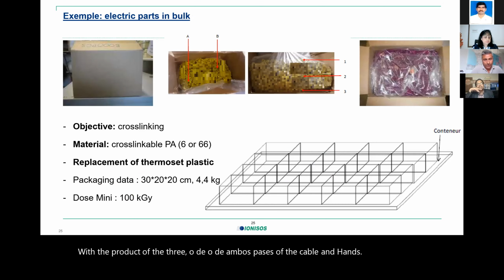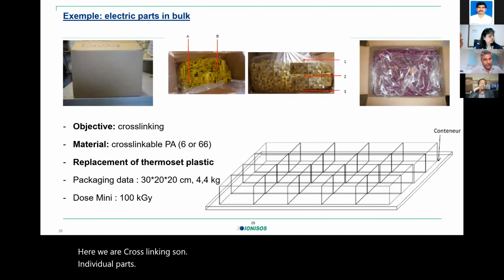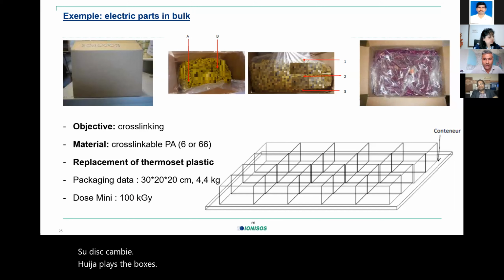Here we have an example that we can look at in more detail. Here we are cross-linking some individual parts made of polyamide. In this case, we receive the products in boxes of those dimensions, 30 by 20 by 20, with a weight of 4.4 kilograms each. So in this case, the target dose can be 100 kilograys. As you can see in the diagram, we place the boxes that we are going to treat on an irradiation tray.